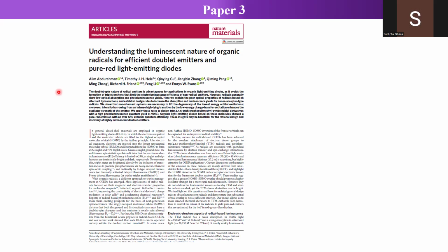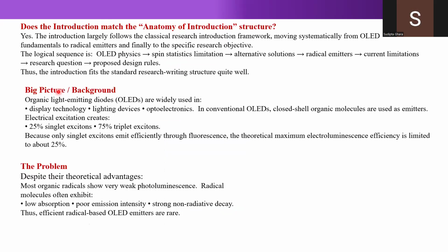So there is no loss or distribution of population over singlet and triplet, which happens in the case of TADF, fluorescence, or phosphorescence type materials. When we talk about the radical system, only one type of energy state is possible, the doublet. So the transition happens only from the doublet excited state to the doublet ground state. So theoretically, we can get 100% quantum yield.